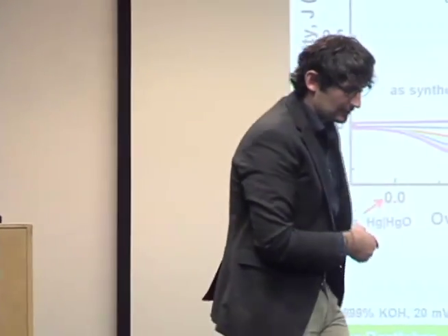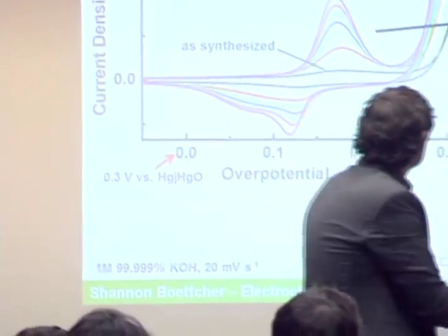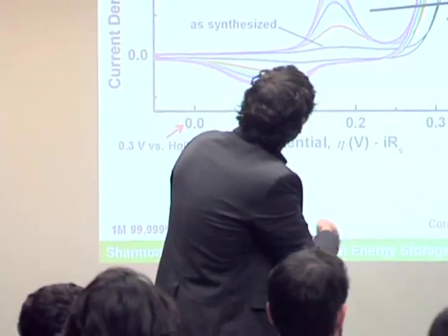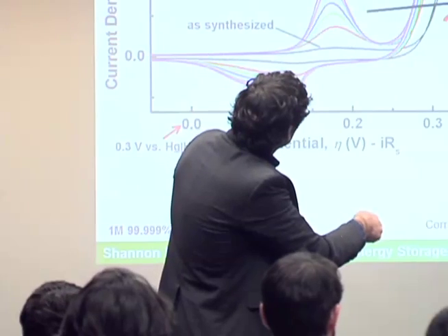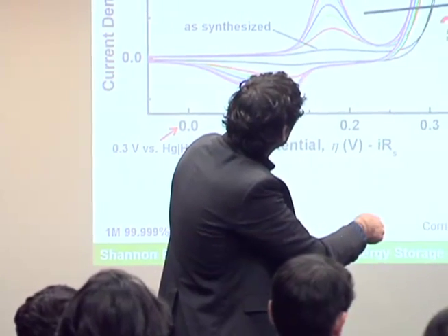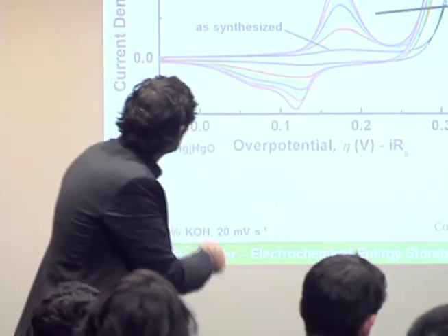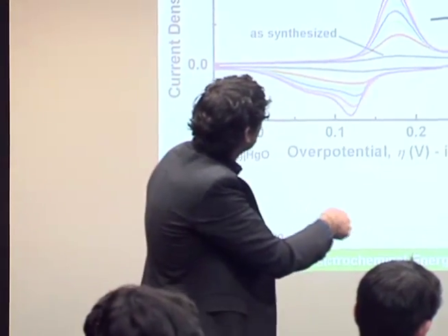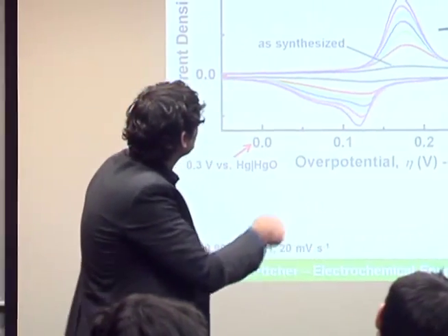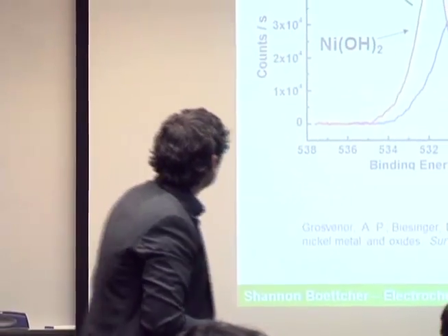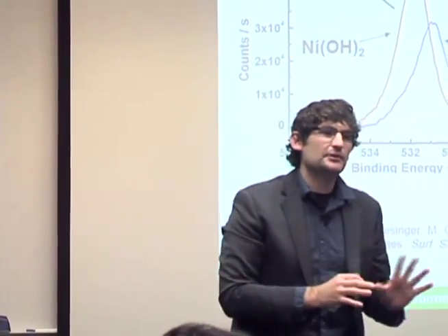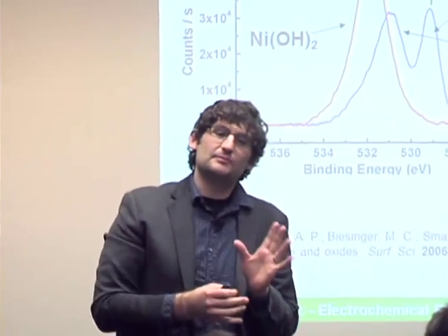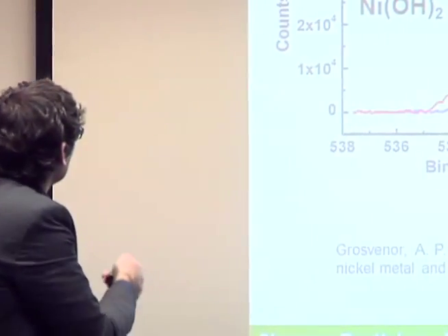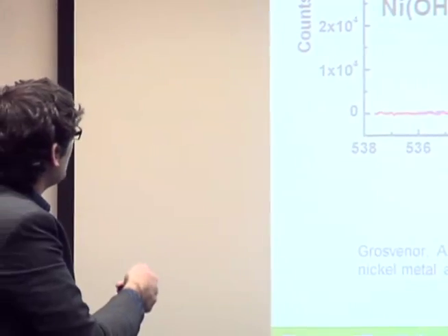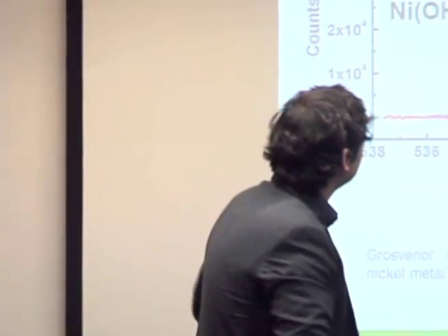Sorry about that. This is consistent with the conversion of the nickel oxide electrode, this crystal nickel oxide, into this oxyhydroxide phase. So this peak is consistent with the oxidation of the nickels from nickel 2 plus to nickel 3 plus. And the fact that the peak's growing in is telling us that we're making more of this layered structure. And I'll talk about this more in a second. And so if you go look at the XPS, you find the XPS spectra are exactly as predicted for these layered structures. So you're starting out in these oxide phases, you're making these hydroxide phases.